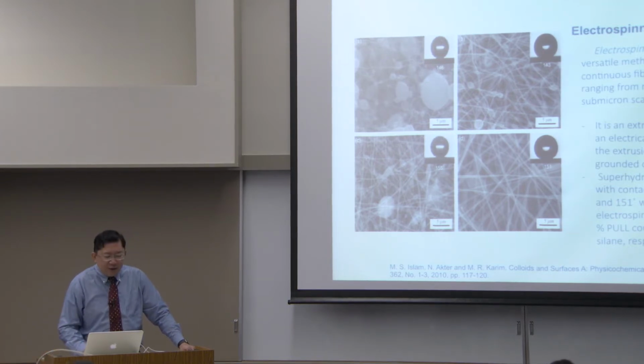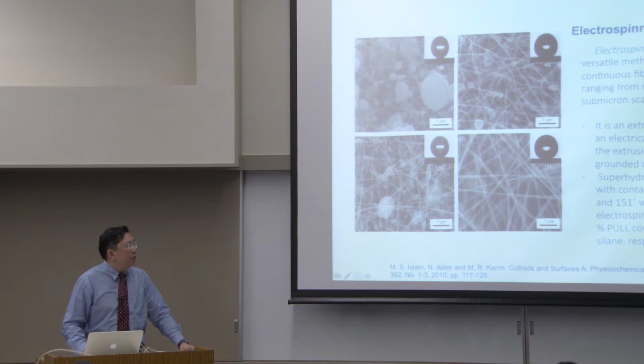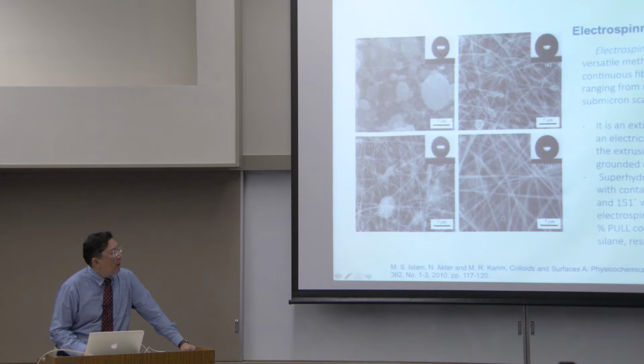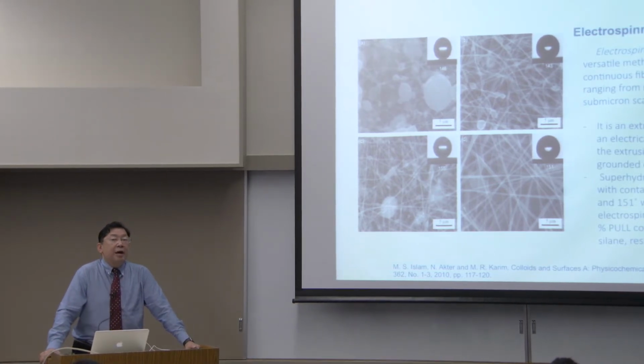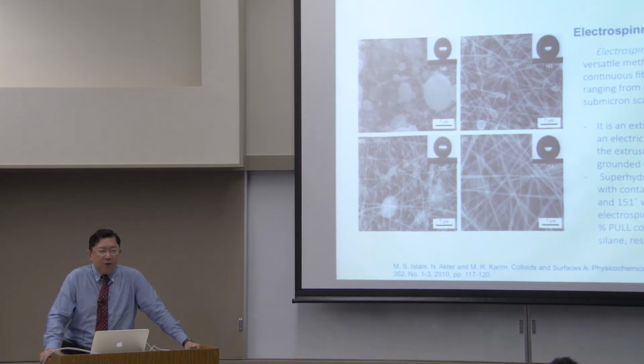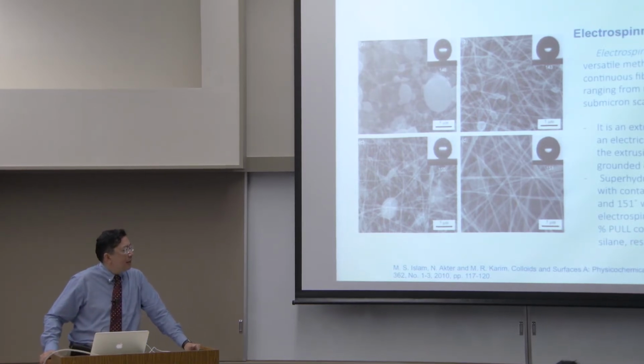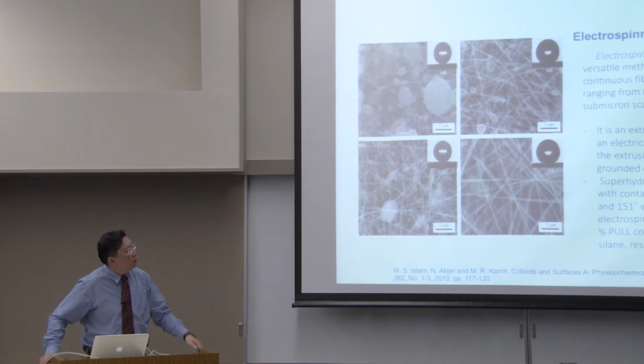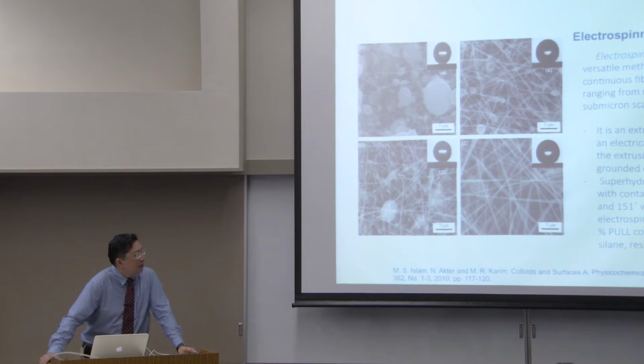The high contact angle can be achieved essentially by using, in this case, a fluorinated silane together with an electrospun fiber. So you can combine different types of nanofiber material by electrospinning or other methods, and then further modify the surface energy using silane agents. All of these surfaces, except for the two above which are below 150, clearly exhibited a superhydrophobic effect.